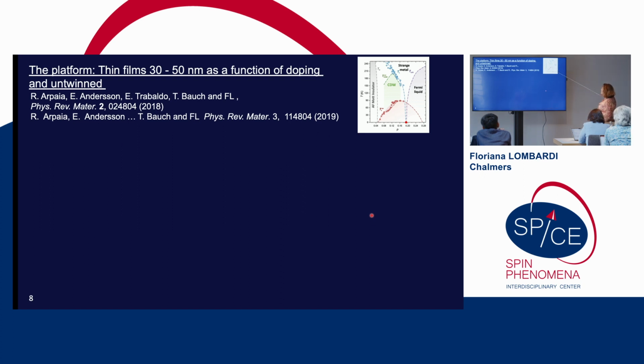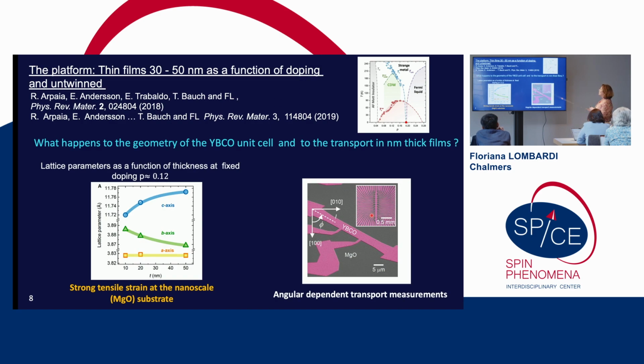So this is the phase diagram that we have for thick films of 30, 50 nanometers that has all the peculiarity that I showed before that is similar to single crystal. And then you go to 10 nanometer films, or even lower. We can grow 5 nanometer films. The first thing you do, you try to understand how the geometry changes. And here we see as a function of thickness that the a-axis is almost constant, the b-axis is extended, so you have tensile strain, and the c-axis is reducing.